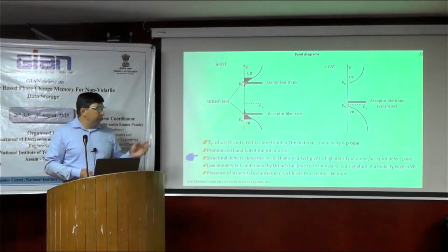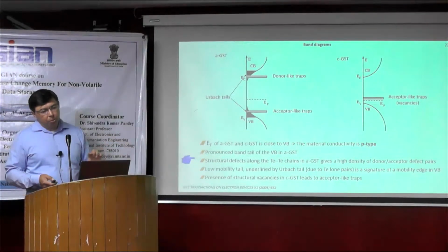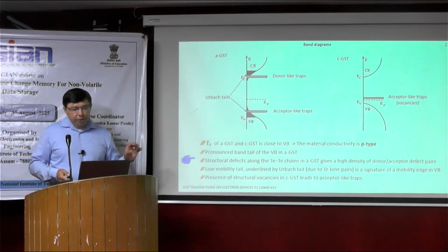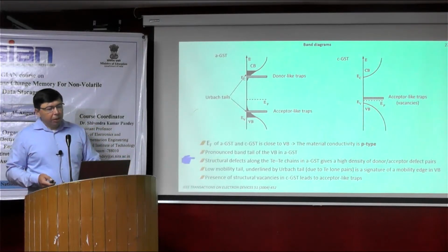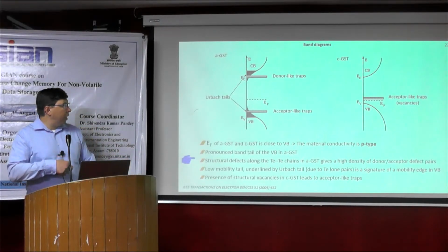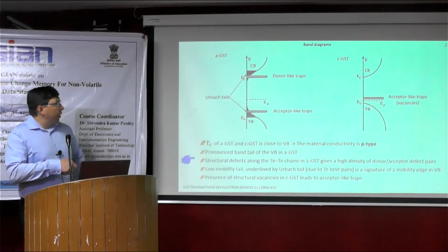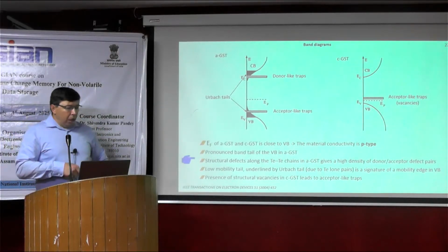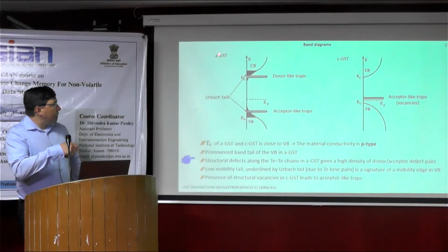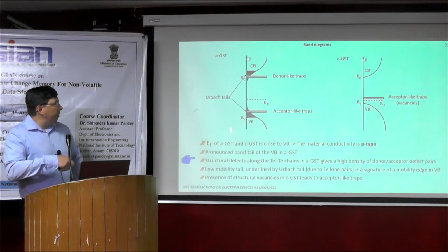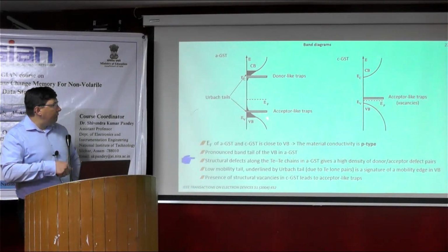From the previous lecture, we already know that the band gap of amorphous and crystalline phase change materials differ. We considered the optical band gap. For amorphous, it was like 0.5. Here it's 0.7. There are some reports on the band diagram, and it's found that in amorphous GST, we have the conduction band and valence band.